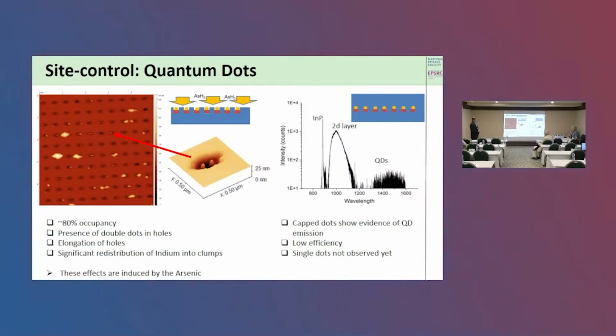So we have to cap these, and again we've capped them in indium phosphide. And we do see evidence of dots. This is a kind of macro PL measurement of our quantum dots around 1400 to 1600. At the moment we don't see single quantum dots. They're quite dim, and that means that we need to optimize the capping process. But at least we do see an optical signature of these dots.